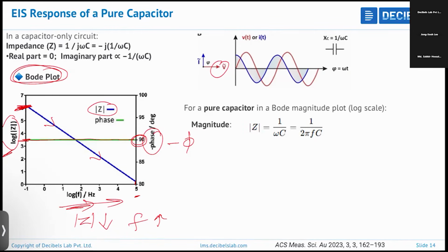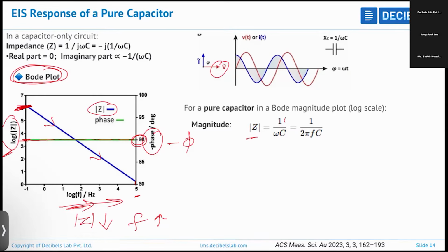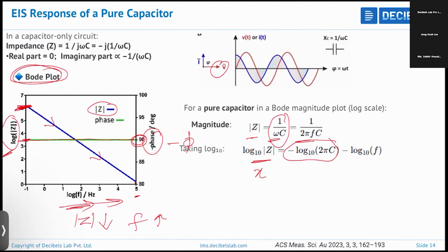So for a pure capacitor in a Bode magnitude plot, Z is equal to 1 by omega C, where omega is equal to 2 pi f. If you take the log of Z, you will get minus log10 of 2 pi C minus log of f. So log of f is along the x-axis and log of Z along the y-axis, and you get this as an intercept. From the intercept you can extract the capacitance. So it is a straight line with slope -1.